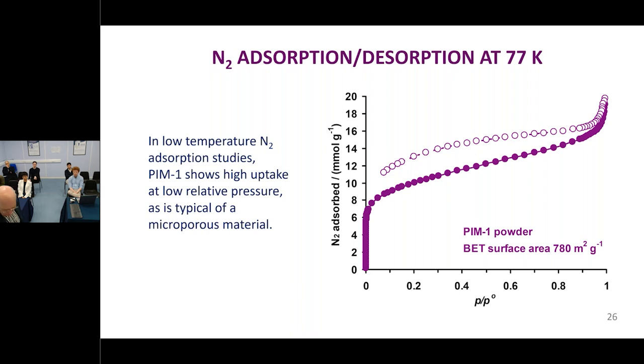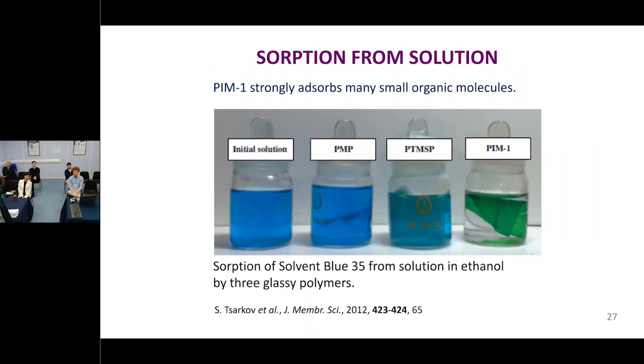And not just gas molecules. It loves little organic molecules. And so here we have an example. We have a dye in solution, it's a phenolic solution, and we're comparing actually 3 different high free volume polymers. But the one on the end, the PIM1, you'll see it's pulled all of the dye out of solution so that the yellow polymer has now turned green with the blue dye. So it loves many little organic molecules.